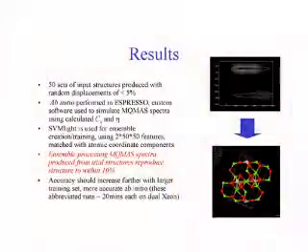So we have 2 grids of SVM ensembles that we simply weight by using the training accuracy, which is one method in the literature for doing this. So the input for each grid element are 50 eigenvalue features, and the output is 1 atomic position component. So just a quick summary of some of the results that we have. This again is just dealing with Forsterite.